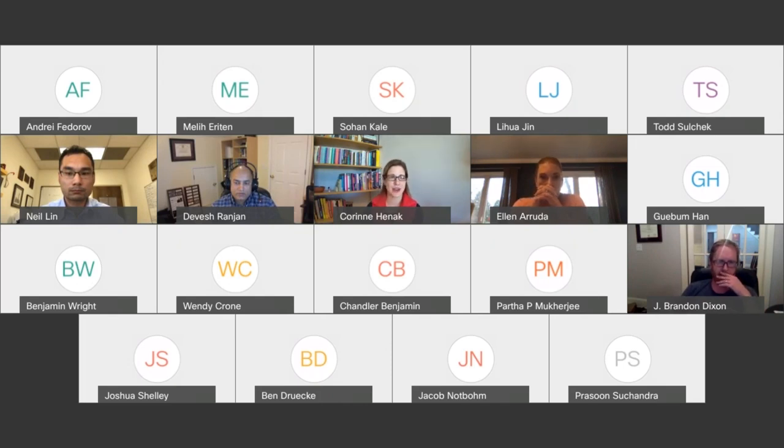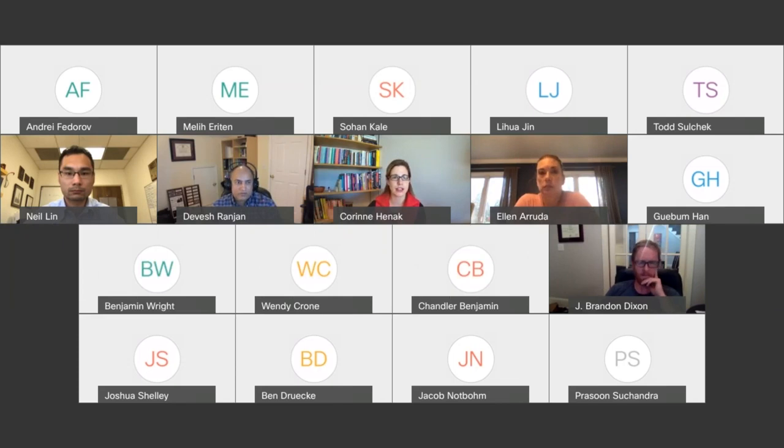Yeah, long-term, that's something we would love to do. What we did initially was just looking at distance in half-millimeter bins from center of impact. It's a crude measure, right? There is going to be some drop-off, but there's also some sample-to-sample variation, just depending on the overall compliance of the sample. They don't all hit the same bulk strains or strain rates. Moving forward, we do also, on a similar setup, speckle the samples, use DIC.